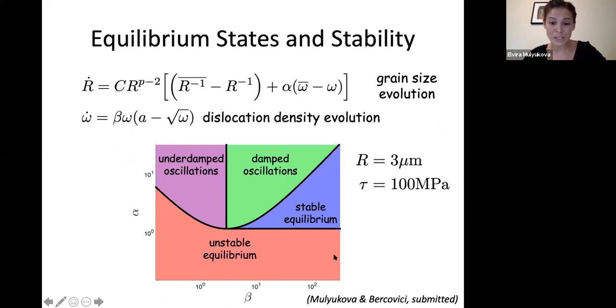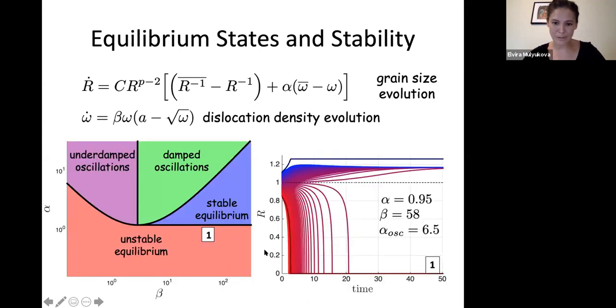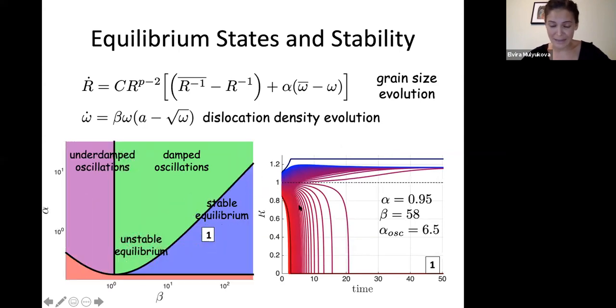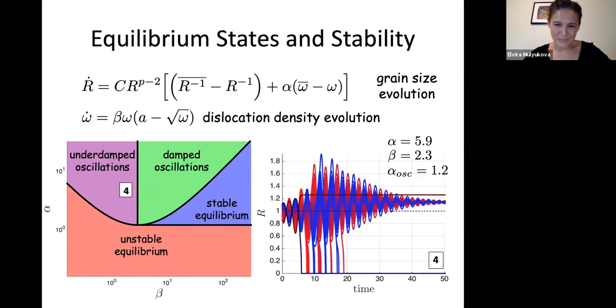We see quite rich behavior that the system may tend towards, characterized by a microstructural steady state that the system may evolve towards. If you start off with time on the x-axis with some ensemble of grains, and you look at where this ensemble of grains goes towards microstructurally, it may undergo something that is similar to a steady state. So it starts off, for example, unstable here. This would be your normal grain growth, and eventually move towards a steady state after gobbling up some of your smallest grains.